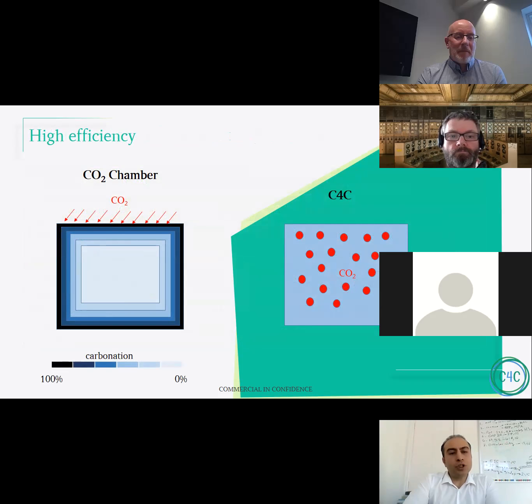So CO2 chamber, when we expose the concrete cast element in the chamber, CO2 will be exposed from outside and then try to penetrate inside. As a result, the external layer will reach the maximum carbonation. The dark color represents maximum carbonation, 100%, while the internal layer is still not carbonated. The method and this procedure is not effective.